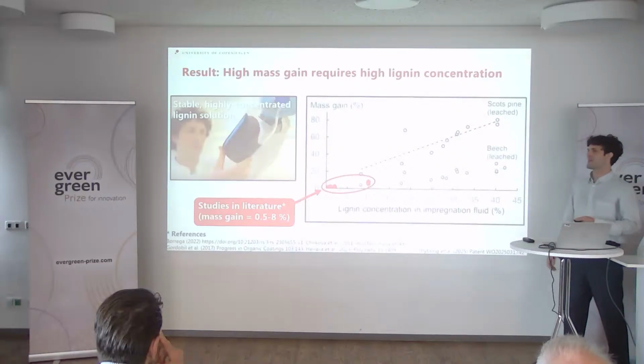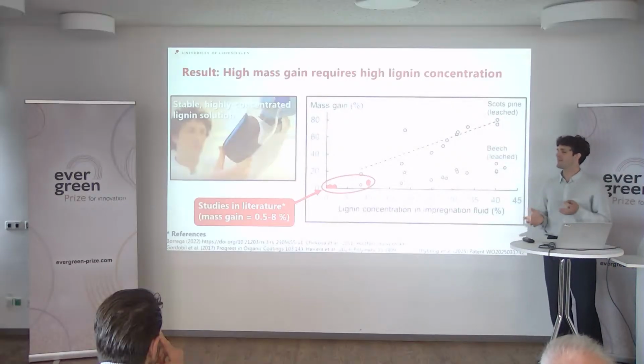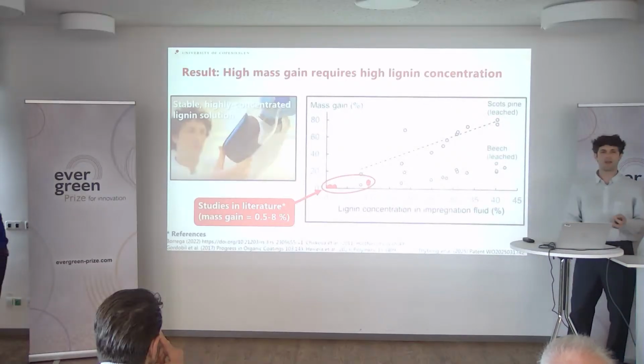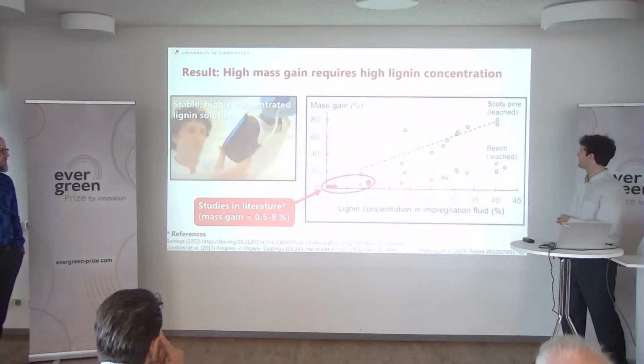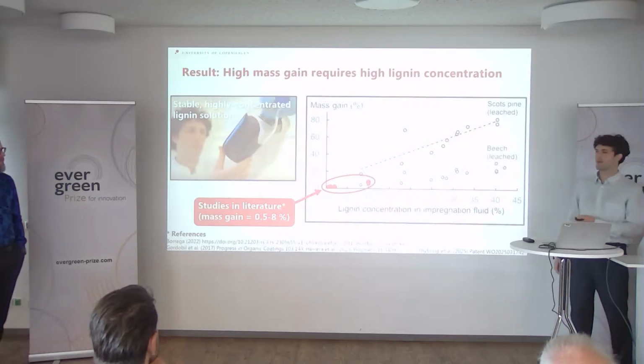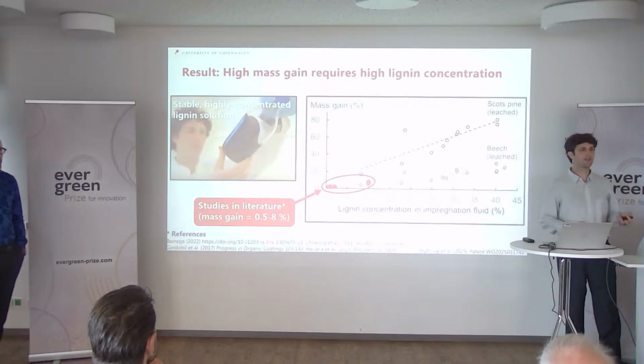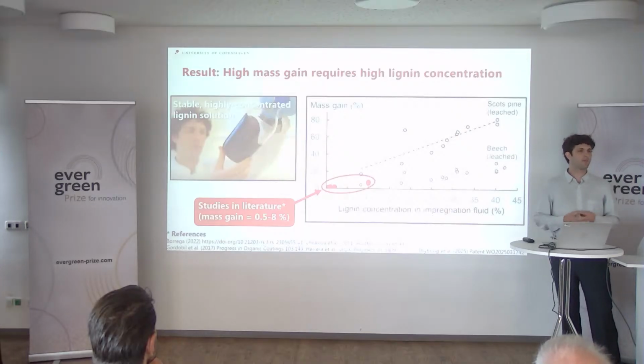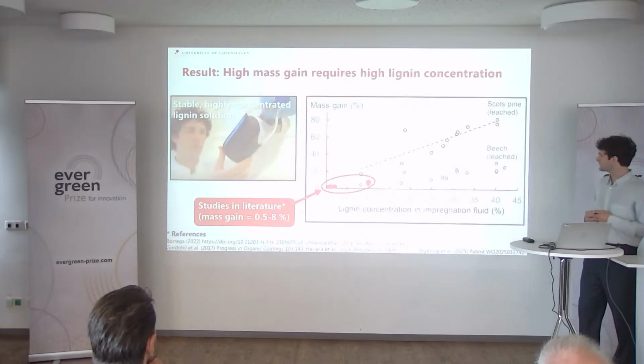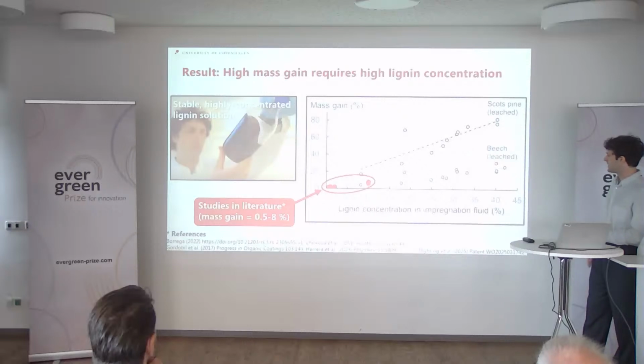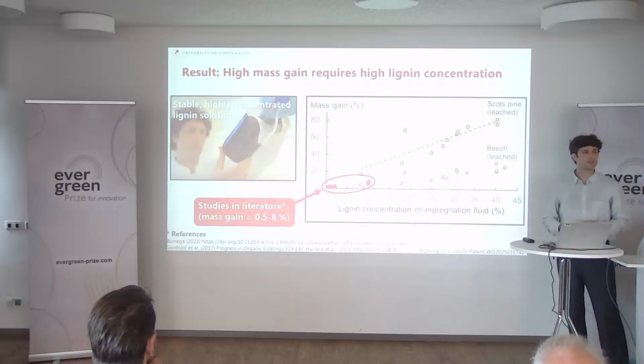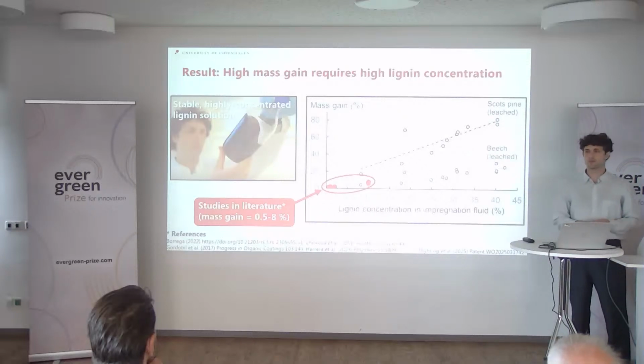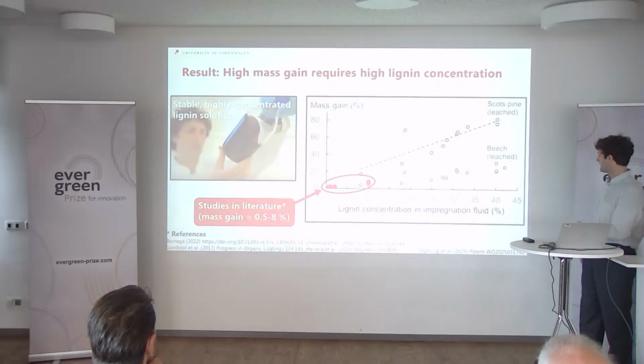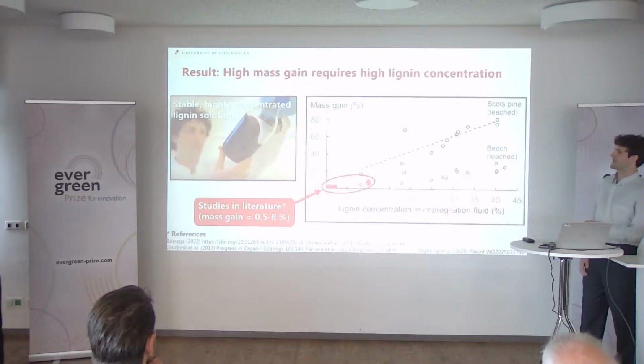So then we kept asking ourselves, playing devil's advocate, why is this working so well? What is the reason why we are obtaining 90% mass gain, which is about 10 times larger than previous experiments in other labs? The reason seems to lie in the concentration of lignin that we can put into our solutions. Since we have been able to develop this solution with high concentration of lignin, we can obtain very high mass gains.